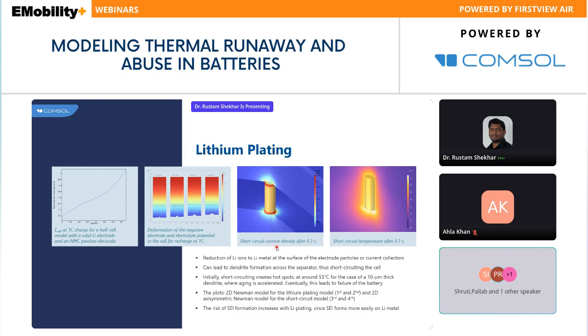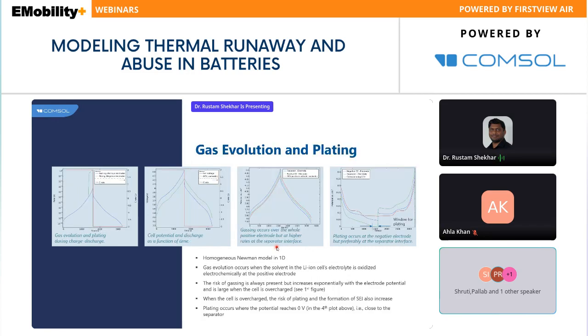you can model. And this will give you an alarm where, let's say, you are working at high C rate conditions and low temperature conditions, and if your dendrite has grown enough to internally short circuit the battery, then this will be one more cause of failure of the battery. So this way, lithium plating again can be modeled. And then the last case study which we want to present in front of you will be the combination of two failure mechanisms.